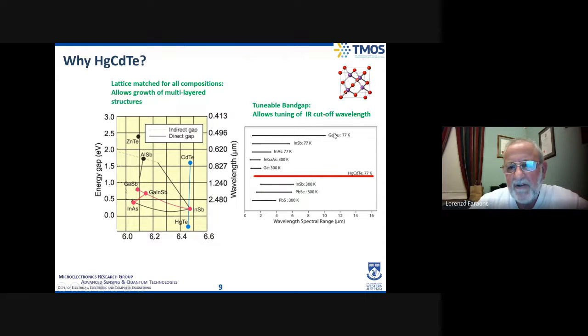So if you look at the wavelength range for those detectors I mentioned, these are other impurity band detectors, which are not really competitive from an imaging point of view. Here's indium antimonide, which cuts off at around 5.3 microns or so, and indium gallium arsenide at about 1.7.